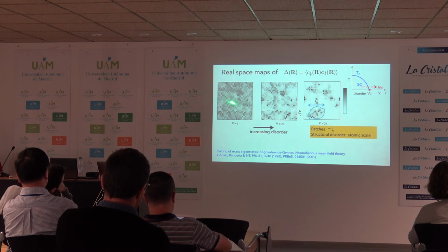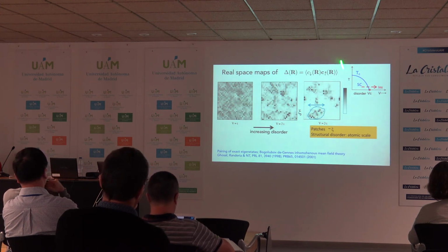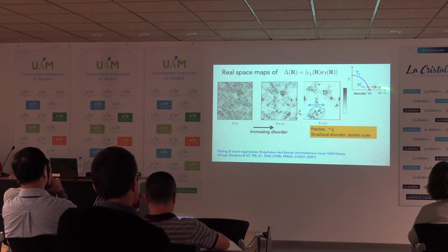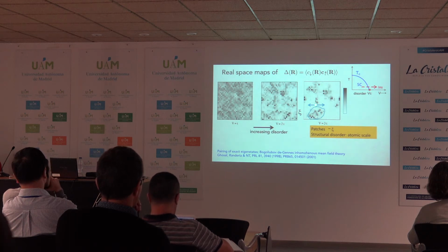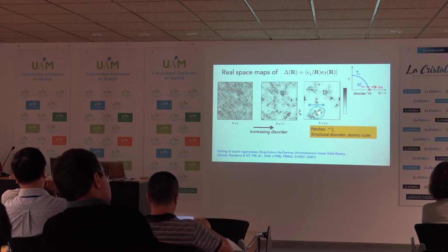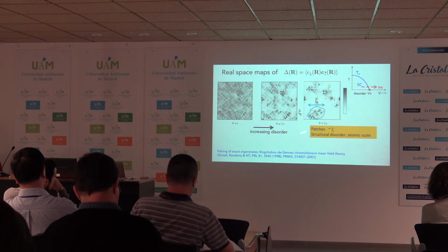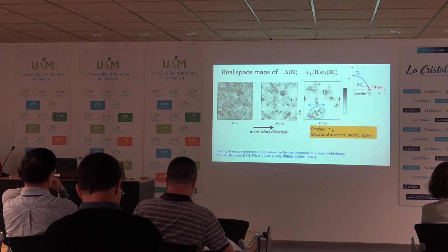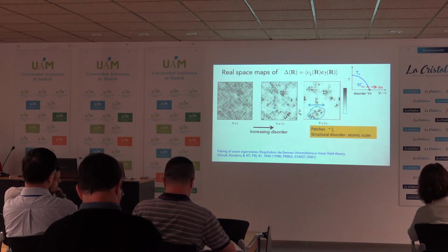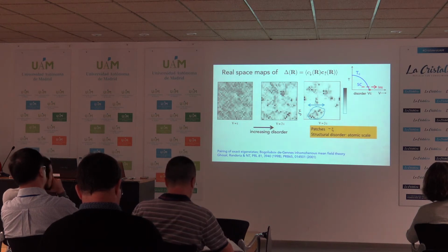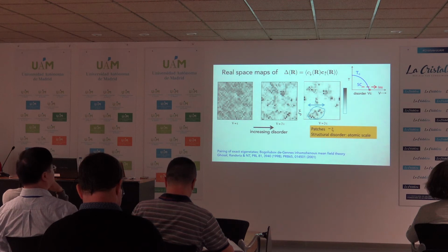So these are now the real results from Bogoliubov-de Gennes calculations. And you see that I'm taking this phase diagram here, temperature disorder at low temperature, cutting across like this. The phase transition where superfluid density vanishes happens somewhere kind of close to this region, and you start to see the formation of these patches or puddles where the order parameter is large, black is large, white is zero. And what I want to stress is the scale of these emergent patches. So the structural disorder is on kind of an atomic scale. So these are not electronically inhomogeneous. They are electronically basically homogeneous. But in the presence of even this homogeneous disorder, what is emergent are patches on the scale of the coherence length xi, some kind of a disorder coherence length. That defines this patch size.